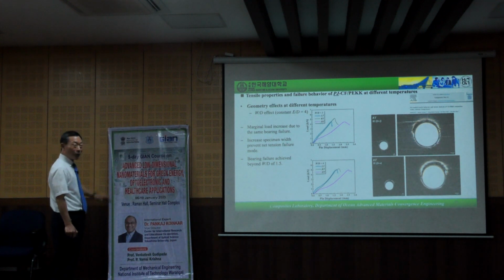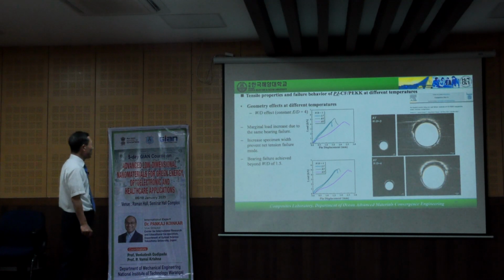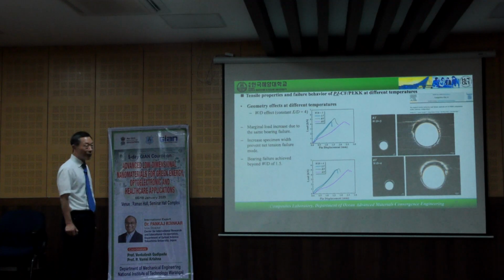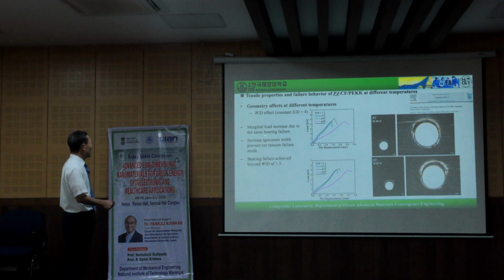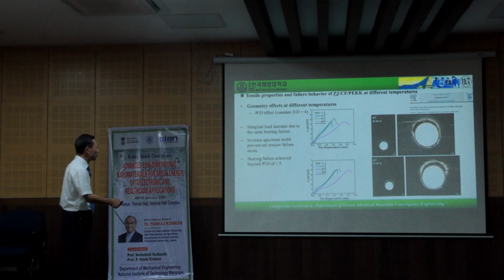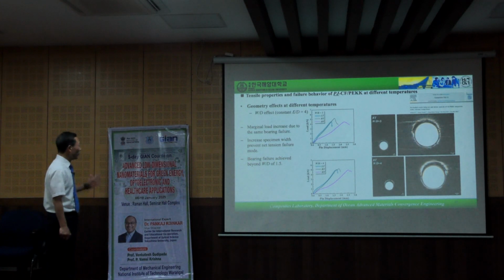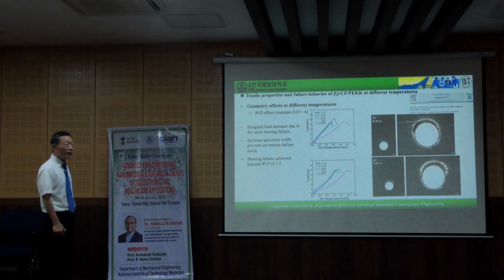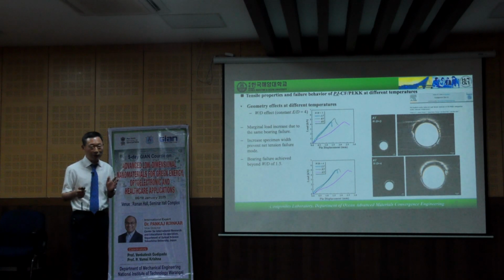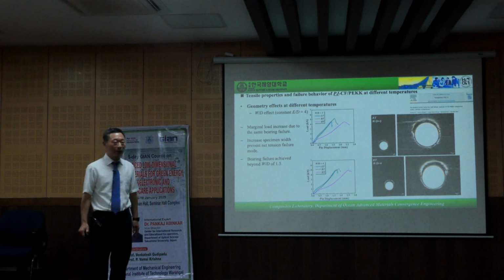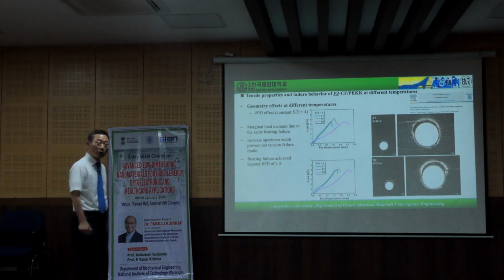So, finally, we summarize like this. W/D effect under constant E/D ratio equal 4: marginal load increased due to the same bearing failure. Increased specimen width prevented net tension failure mode. Bearing failure achieved beyond W/D ratio 1.5. Very important result.